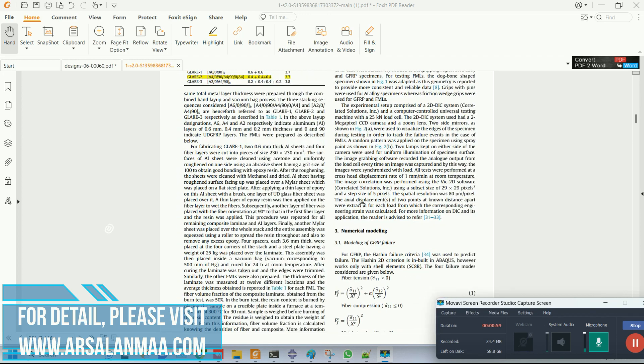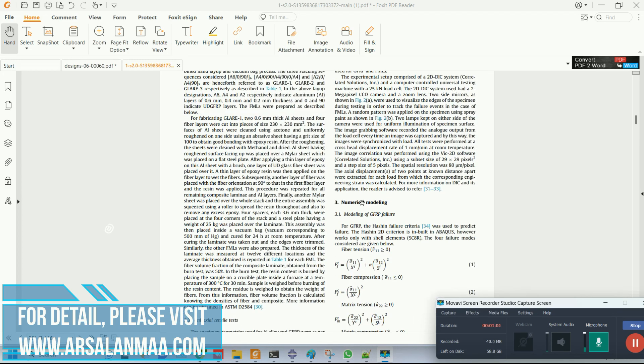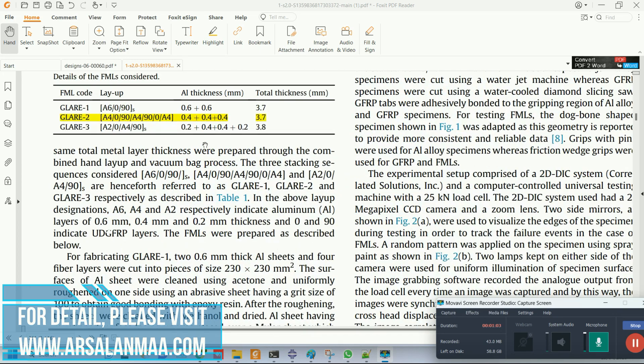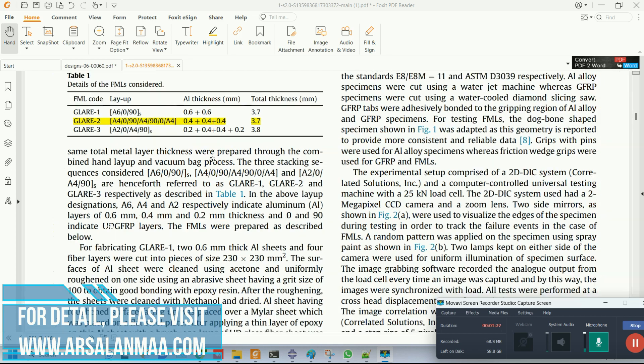The orientation of this composite is as follows. We are going to model this GLARE-2 specimen, and this sequence indicates A4. The first layer is A4, which is aluminum with a thickness of 0.4 mm. Then there is GFRP with a layer orientation of 0°, then again GFRP with 90°, then again aluminum, and the sequence goes on. The overall thickness of this composite is 3.7 mm.